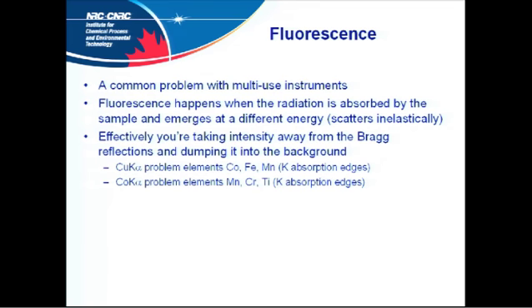The common issues in terms of the most common tubes, for copper radiation, you're really looking at cobalt being really nasty. Iron is one that crops up very frequently. Manganese can cause a few problems. With cobalt, the really bad ones would be manganese, chrome, and titanium. Now, you may notice that manganese crops up in both of those. That's a particularly nasty one to have to deal with if you don't have some kind of way of dealing with it.